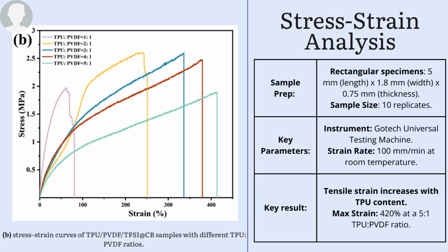The graph on the left illustrates the flexibility profile. The composite with a 1-to-1 ratio appears to be relatively rigid. However, as the TPU content increases, represented by the teal line for the 5-to-1 ratio, a substantial increase in strain capability is observed. So this study achieved a maximum elongation of 420%.